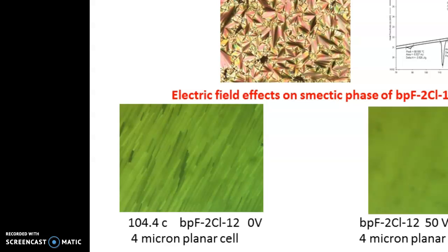The polarizing optical microscopy showed that the lower homologues of all the series showed nematic phases, which are low ordered phases, and the higher homologues showed highly ordered phases, which is a smectic phase, and these textures were further complemented by DSC studies as well. Out of all the series, I could see that the fluorobiphenyl derivatives showed polar phases, which was ascertained by using electric field effects.